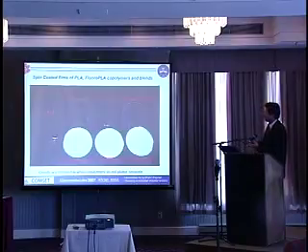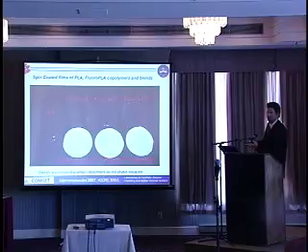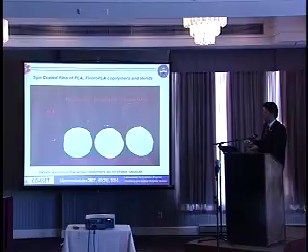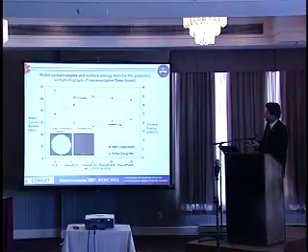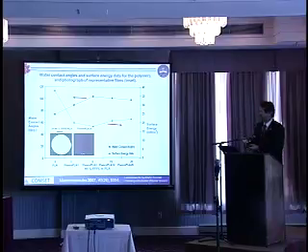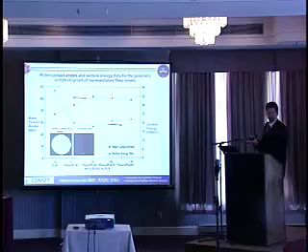Just for an example, this is PLA quenched. It's a semicrystalline polymer, but you can quench it so that it's clear. And then here are the copolymers, optically clear, very good miscibility, and these are the corresponding blends, which of course phase separate. And the fluorocarbon goes to the surface. This is what's interesting. So after about 1 weight percent of this perfluoropolyether blooms to the surface, forms a nano-structured, nano-roughening on the surface, and gives you tremendous drops in water contact angle and increases in surface energy right away with just a little bit. So what's the impact on this in a tissue engineering material?